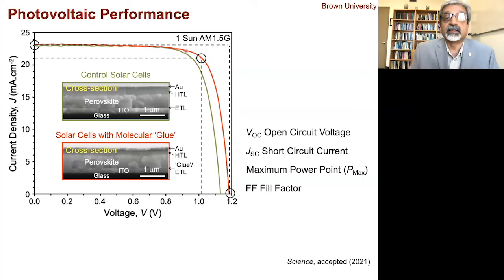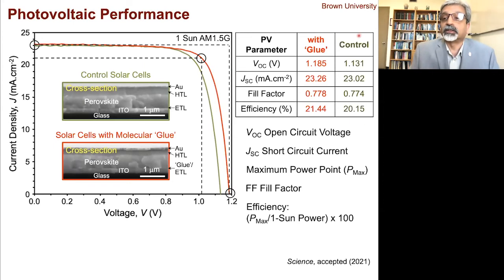So you want these curves to be as square as possible. If it becomes less square, then the fill factor becomes less than 1. So you also want to maximize the fill factor, approaching 1, in order to get the maximum out of this solar cell, right? And then the efficiency is basically this Pmax divided by the 1 sun that we put on, multiplied by 100. So these are some numbers. The control, you can see, is about 20% efficient, whereas with the glue, we not only improved the toughness, but we also improved the efficiency.